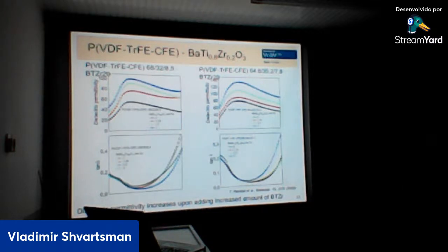Does the dielectric breakdown strength also follow a Weibull distribution for polymers? Yeah, the Weibull distribution is a statistical model in materials science. It actually comes from structural mechanics. I asked this because I'm more familiar with the concept of Weibull distributions being applied to fragile materials, not polymers themselves. Of course, from the mechanical point of view it will be different, since the elasticity of polymers appears quite fast, and they have different kinds of mechanical deformations than ceramic materials, but electrically they are not so different. And we speak about electrical breakdown, not mechanical. Okay, thank you.